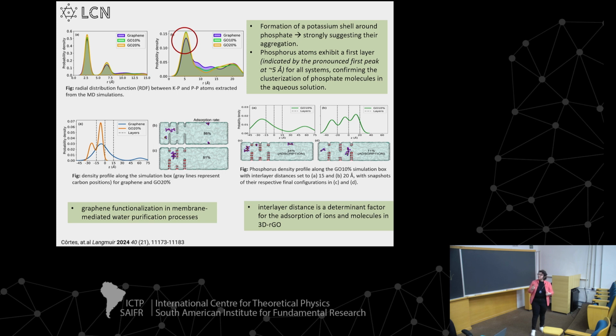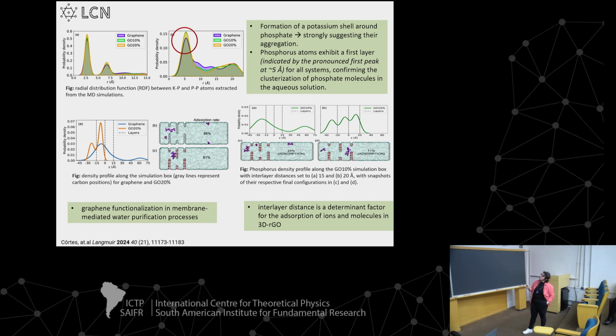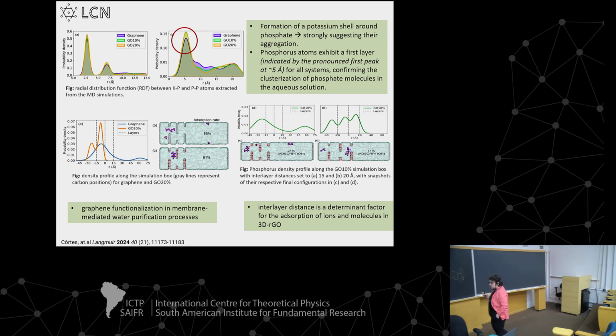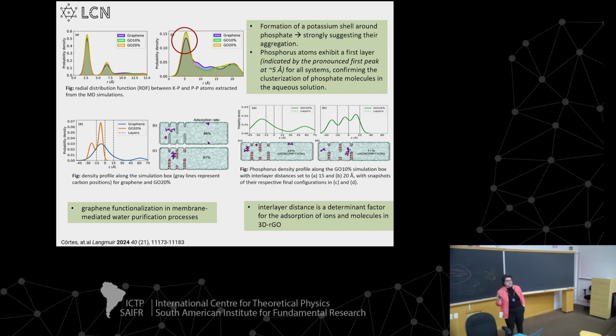to these layers more than when we have a reduced material. Also, we show the formation of a potassium shell around the phosphate, the contra-ion, which strongly suggests an aggregation. This is new information that we never saw in other works.